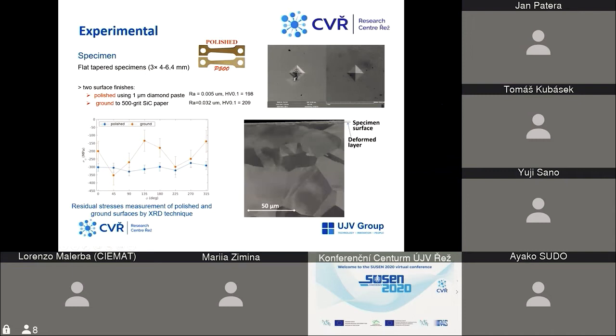Compressive residual stresses were found on the polished surfaces, of about minus 300 megapascals, and for the ground surface it was a bit different, which corresponds to, as you can see here, the grooves during the grinding procedure. Also on the ground surface, one can see the deformed layer under the surface caused by the grinding.